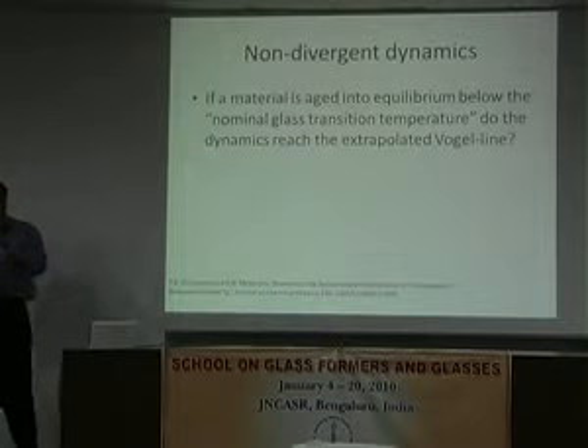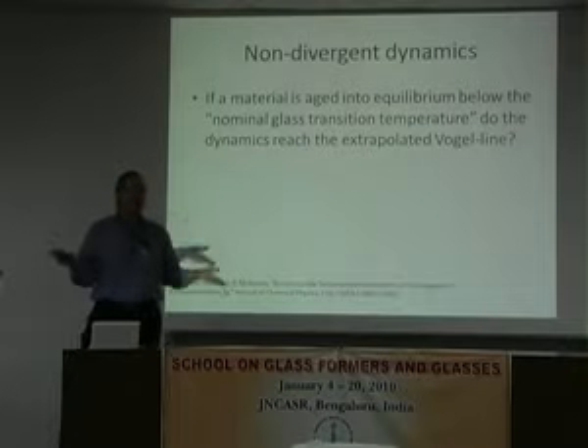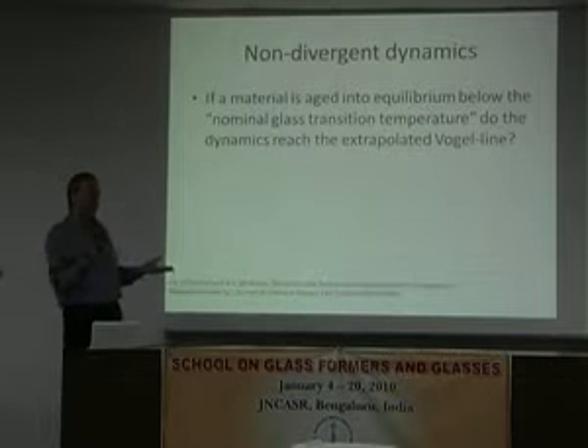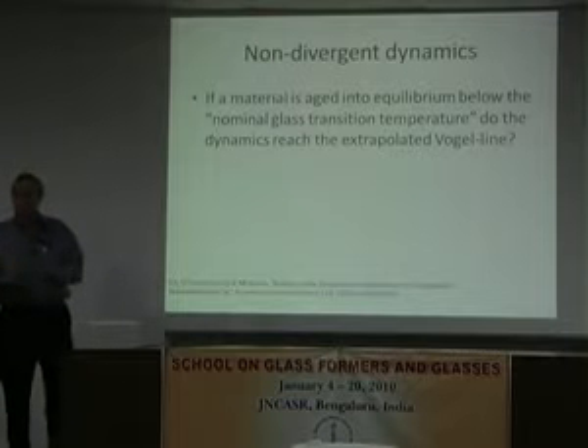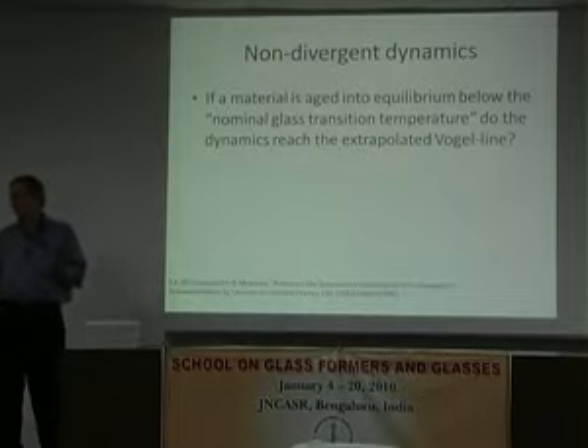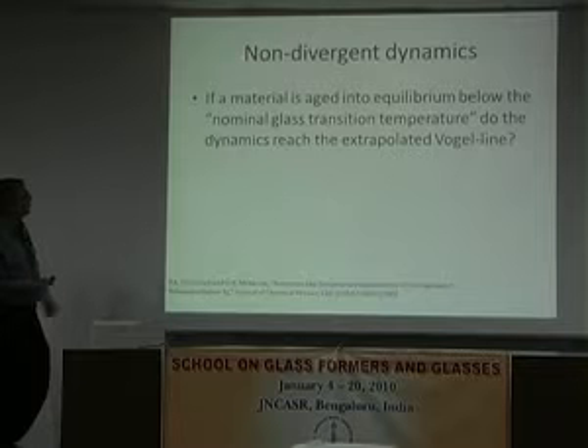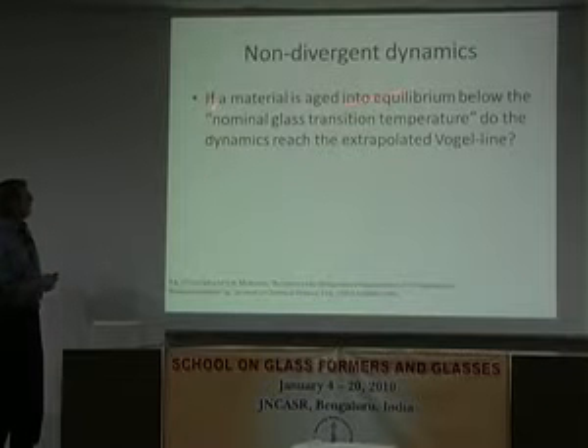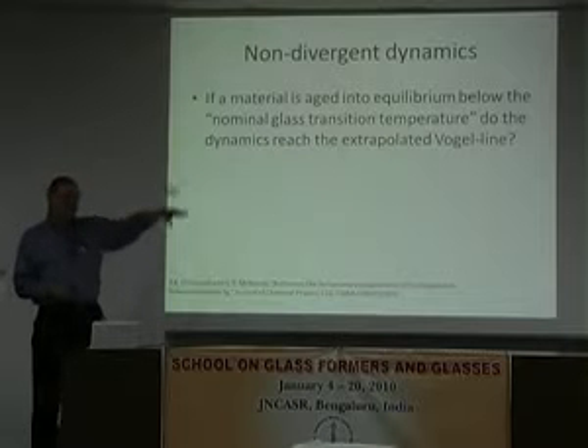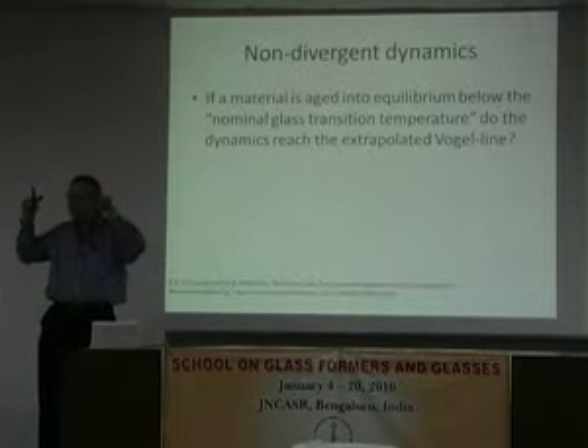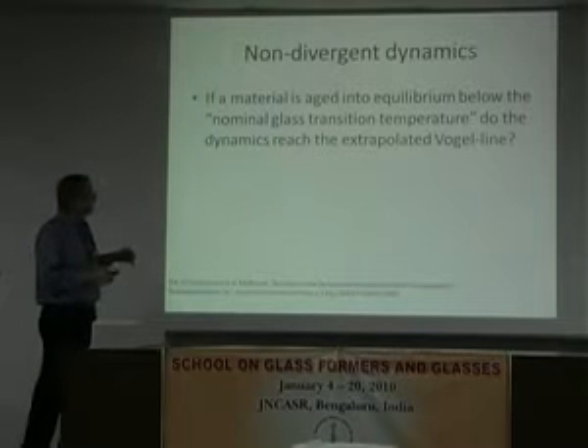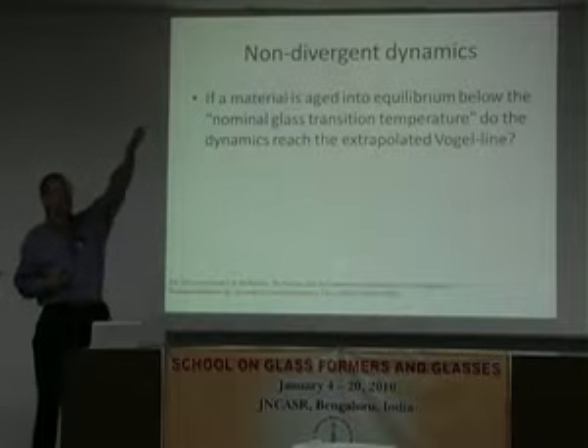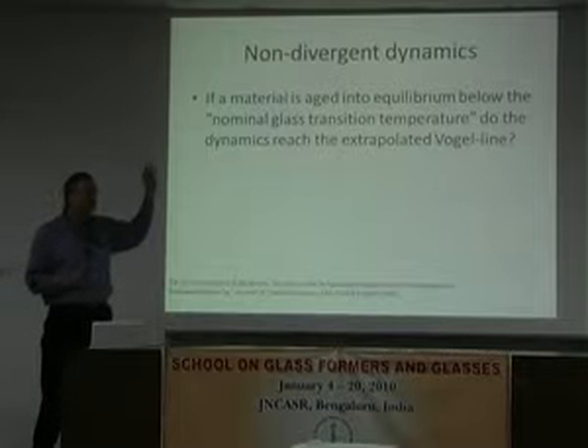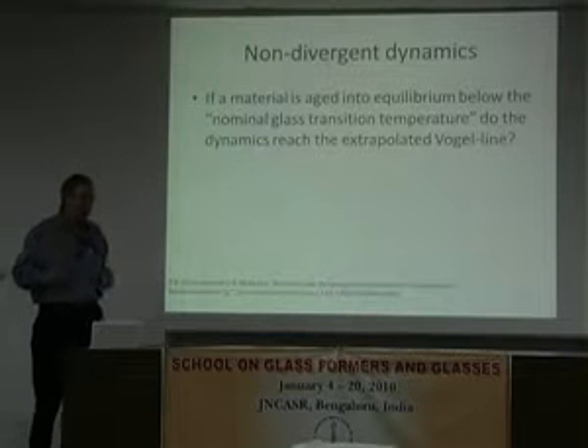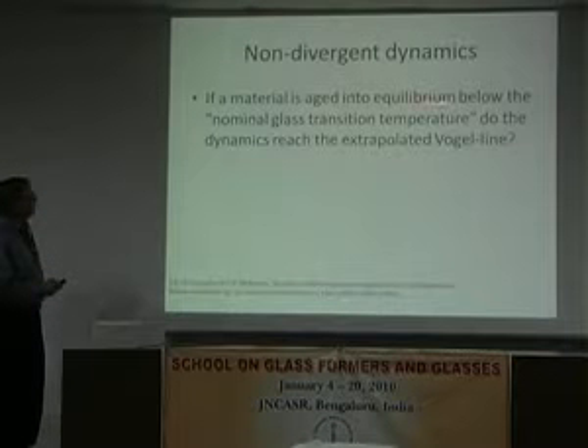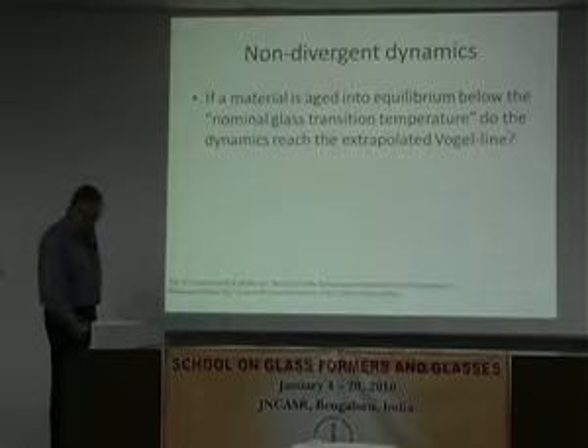So now I understand aging, at least phenomenologically. I understand aging in the linear viscoelastic regime. So it suggests maybe I can use this understanding to carry out some experiments to test ideas. One of the ideas that we were interested in testing was this issue of non-divergent dynamics. If we age the material into equilibrium below the Tg, the conventional glass transition, does the aging curve shift upwards to the Vogel-Fulcher line, or does it go somewhere else? Because this is actually a question that people have been asking, and we actually did this work back in 1999. So what we want to know is, do the dynamics reach this extrapolated Vogel-Fulcher line?